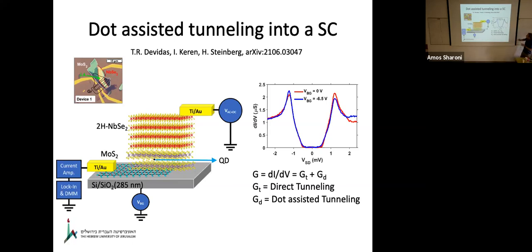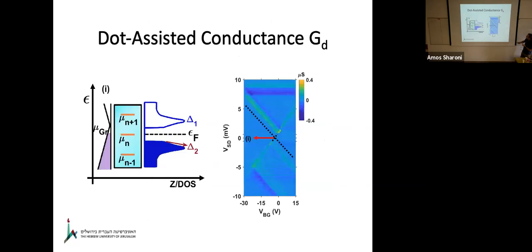That's a dI/dV of the junction, which looks very much like an Ohmic conductor, but if we apply a gate underneath the graphene, we see that the dI/dV changes. Now, we subtract the average contribution of the tunneling junction. And what we get is something that looks very much like a Coulomb diamond with a gap in the middle. The gap in the middle is a superconducting gap. The reason is that if you're on resonance from the graphene source, you hop through the dot and you gap. So there's a certain range of forbidden energies.